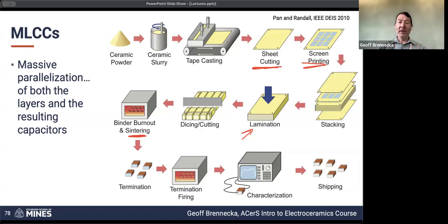It might bend and warp all over the place. So the sintering part is extremely difficult to optimize for each one of these. One helpful aspect of it, though, is that at least the metal layers that we're using, we want them to be as continuous as possible, because if there are any discontinuities in the metallic layer, then that will reduce the amount of capacitance that we'll get out of the part, and it will reduce the amount of energy that we can store within it. But having a discontinuous metallic layer is much less bad than having a discontinuous ceramic layer. So if we have a hole or a pore or a gap in the dielectric layer, that makes it way too easy for charge to flow through there and short circuit.